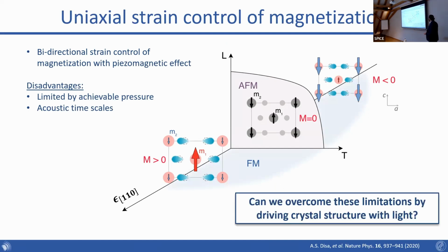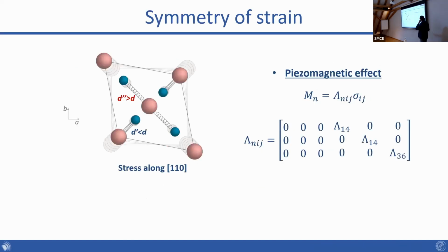Okay, so the question is, how can we overcome this? And can we do this by driving the crystal structure with light? And as I'll show you, we can. But what we need to do is find a way to recreate the essential atomic distortions that are driving this particular effect, which is the antisymmetric distortions of these in-plane cobalt fluorine bond lengths, right? And so to get a clue on how we can do that, we can look at the piezomagnetic tensor in this material, which is shown here.